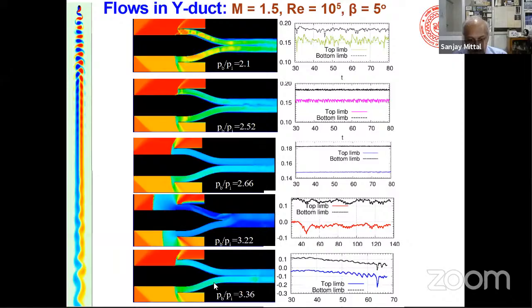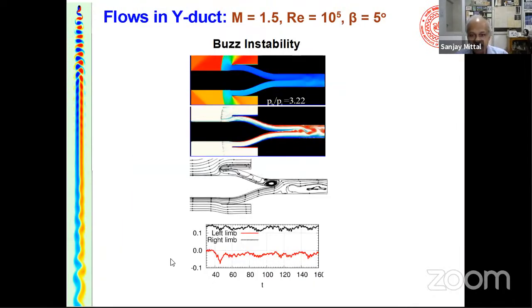And I would like to particularly show you a case of a buzz. So here, the side slip angle is 5 degrees. So the aircraft is actually at a side slip angle. So it's getting more mass flow rate through the lower limb as opposed to the upper limb. And here is a close-up picture of that situation.